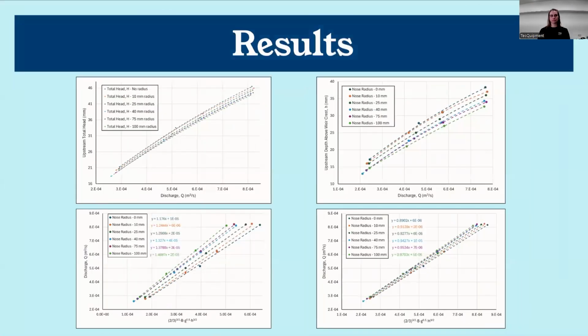The top graph, showing upstream total head and depth above the weir crest versus discharge, illustrates that the smaller nose radii result in higher head and depth. This translates into the bottom graph, where the discharge coefficient, represented by the slope of the trend lines, increases with larger nose radii, improving hydraulic performance over the weir.